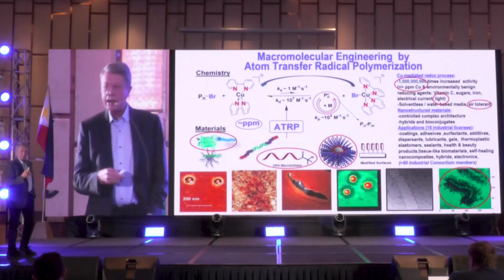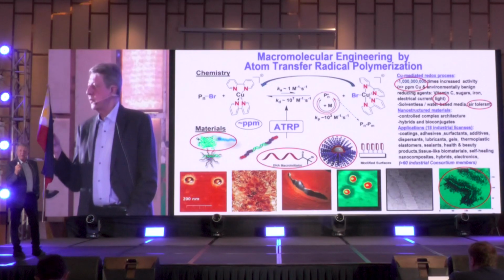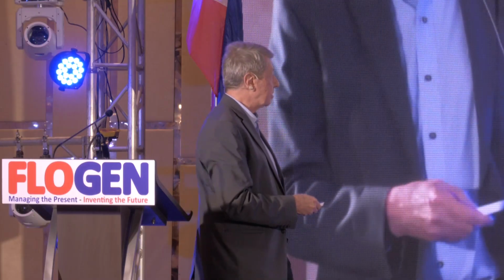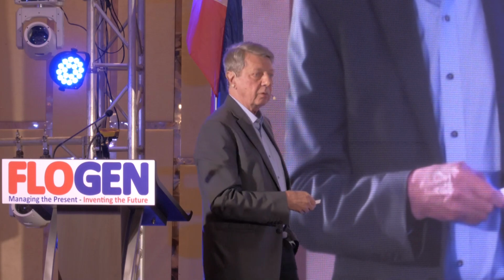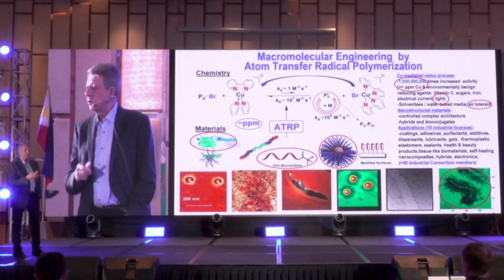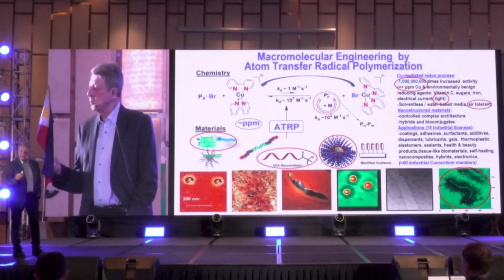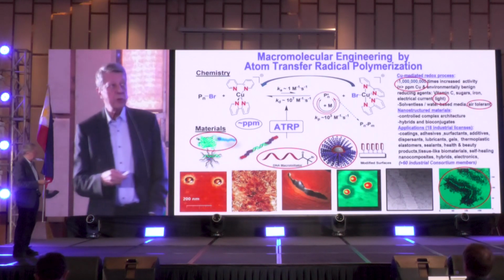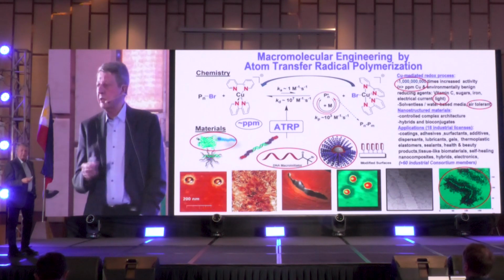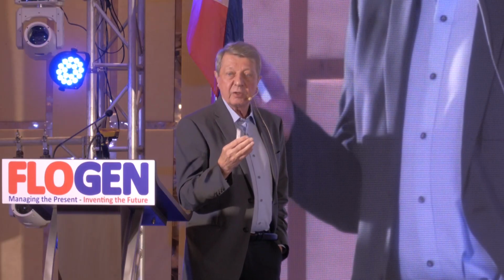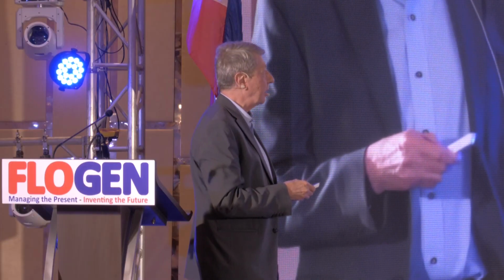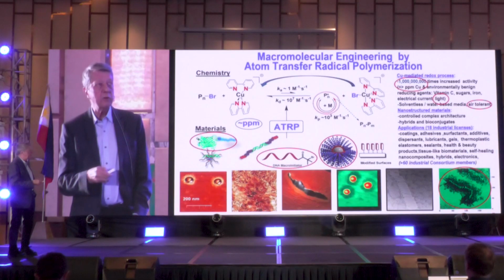I mentioned to you that in a radical polymerization, why we decided to look at radicals, because they are very tolerant to many impurities, but also to many functional groups. They can be combined with proteins, with nucleic acids, making bioconjugates, linking polymer to protein or to nucleic acid. But the challenge in a conventional radical process was that after 1,000 monomer additions, after 1 second, there was a termination event. You could not make these materials anymore. So it was necessary to extend the life of the growing chain from a second to minutes, hours, or days. And we do that by equilibrating these radicals with so-called dormant species. Dormant means sleeping. They cannot propagate, but they cannot terminate. You need to wake them up by using some kind of catalytic system, consisting of an activator and deactivator.